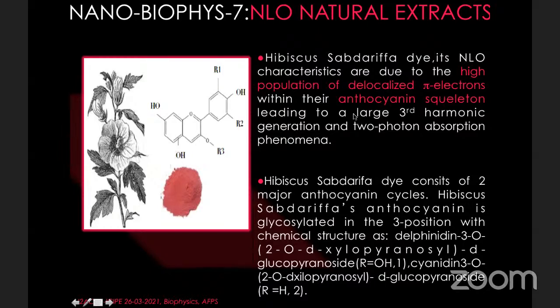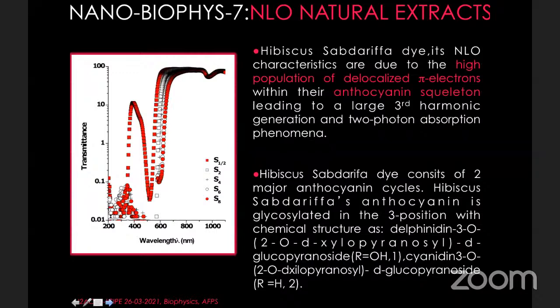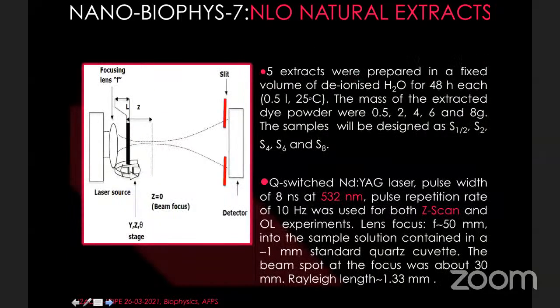And so, if there are pi electrons, therefore there is a chi-3 behavior. For such, Siddiqui has investigated their properties, and he found there is an absorption within the visible and near infrared edge. And therefore, indeed, if we come with a laser within that range, we will be able to measure the chi-3. So he took 532 nanometers, neodymium-YAG doubled frequency, and used the standard Z-scan technique, with the open and closed aperture, this well-established optical method.